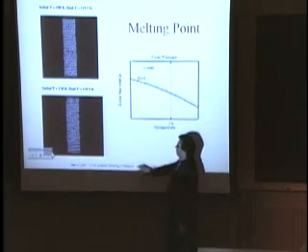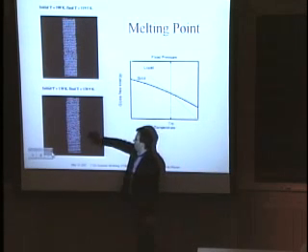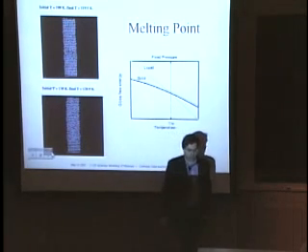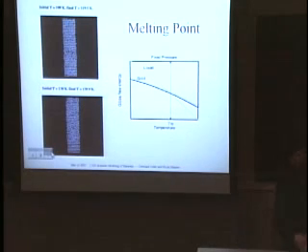The caveat in doing this kind of simulation is that they are still very expensive to do ab initio. You usually need at least 400 or 500 atoms to do such a simulation and to kill the finite size effects. And this is even now borderline for what we can do, even for the simplest elements.